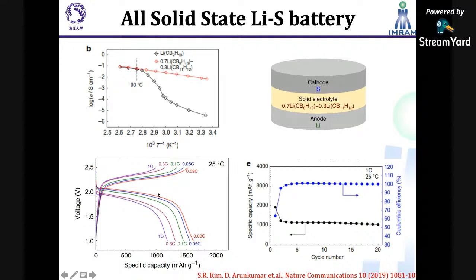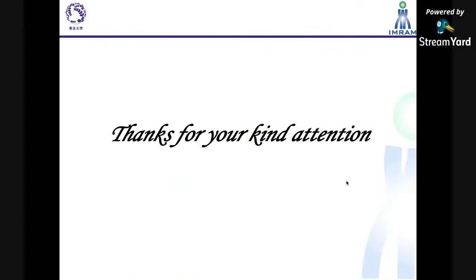And this battery is shown to have a specific capacity of about 1000 milliampere hour per gram, which is about 4 times higher than the present generation lithium ion batteries. Therefore, by developing an all solid state lithium sulfur battery, we can have high energy density and high capacity batteries. So with this I will conclude my presentation, and thank you so much for your kind attention.